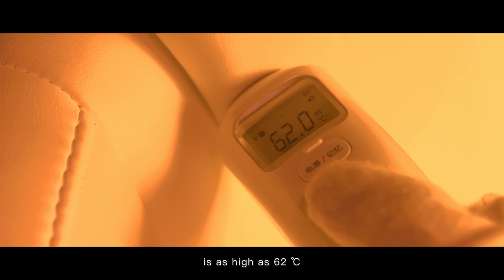We specially built two totally enclosed glass spaces of the same size and placed inside heaters of the same brand and power, as well as the same thermometers. The difference is that we have applied EASYTO RE coating on every surface of Space 1. When the temperature rises to 40 degrees Celsius, we turn off the heaters at the same time. After cooling 2 hours, we can see that the indoor temperature of number 1 glass space is 32 degrees Celsius, and that the number 2 space is 19 degrees Celsius.